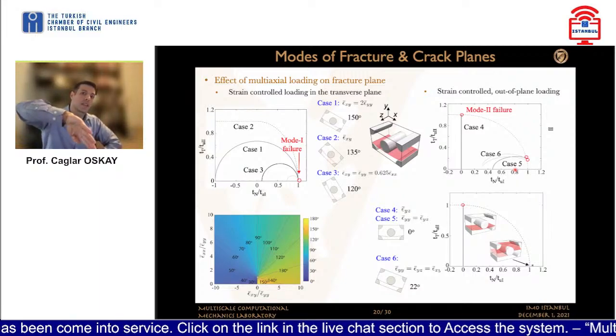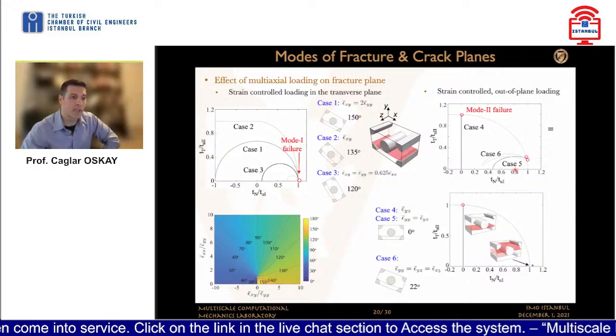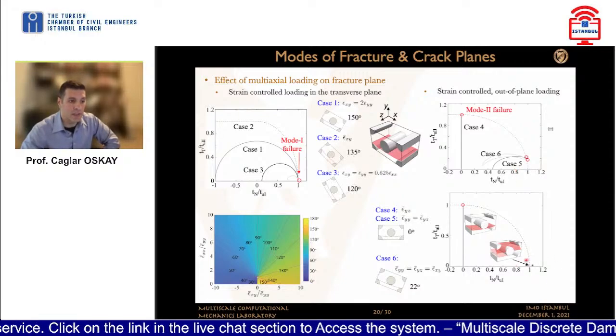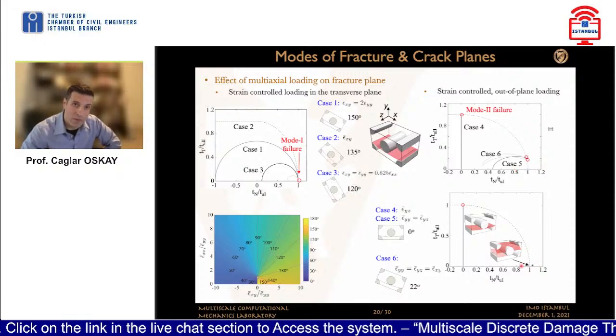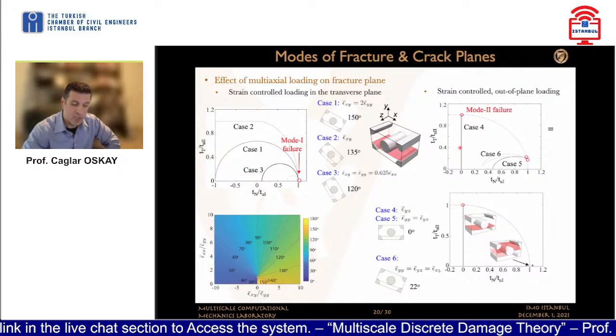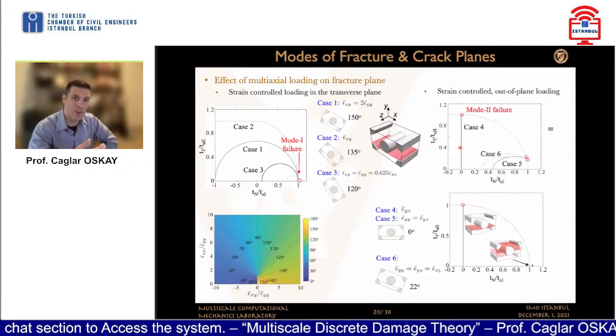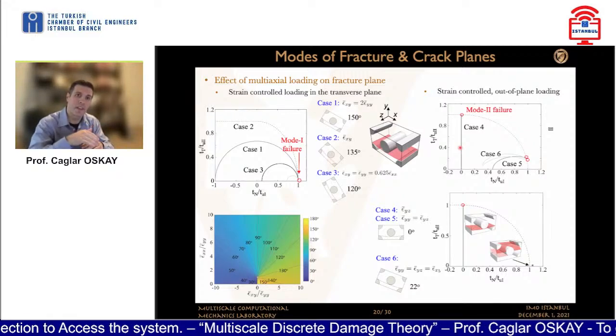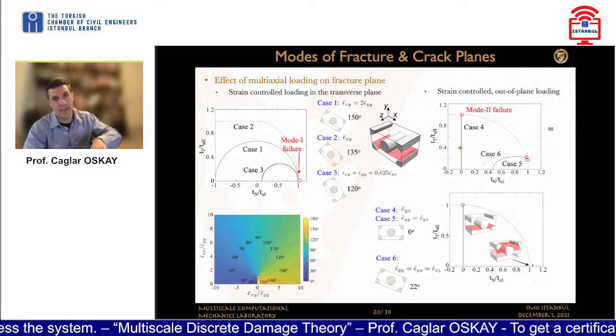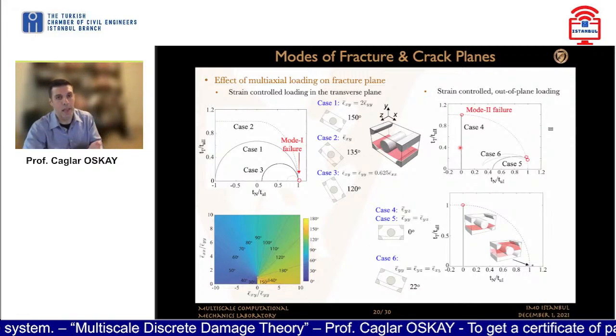But note that in these cases, what we're looking at is an orientation of the failure planes only. If you start looking into other directions, we start observing that there are possibilities of mode 1 failure cracks as opposed to the mode 2 failure cracks that we have found as well. So one has to be a little bit careful, and this calls for a hybrid strategy where you need to have some failure planes incorporated into the model in the off axis, and the primary failure plane that will be captured by the rotation idea.